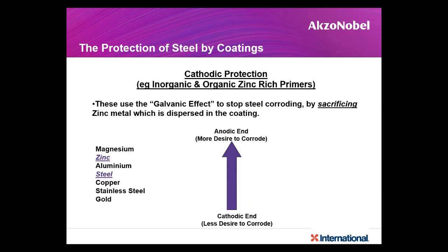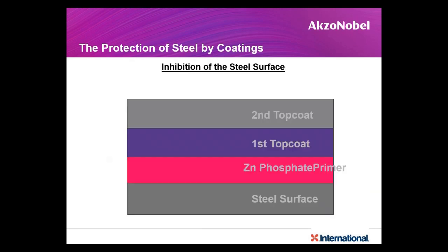So keep in mind, cathodic protection is one method of protection of steel. When cathodic protection methods are applied, this is at the electrical contact. That means the material of construction, that is steel, should be in direct contact with that zinc. That means it should be the first layer on the steel. So primers are generally zinc rich. Keep in mind, you cannot apply zinc rich paint over another primer and expect that it will work. It will not work.